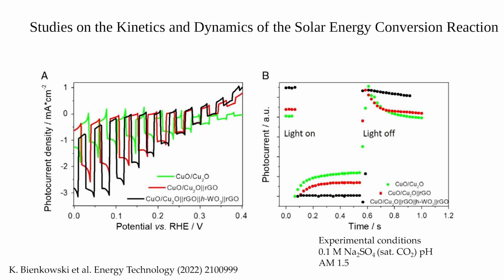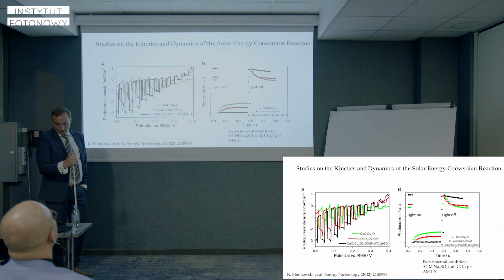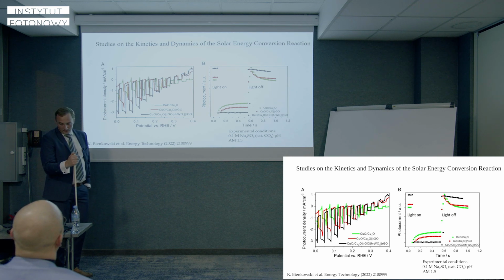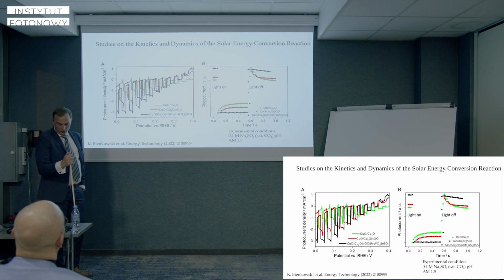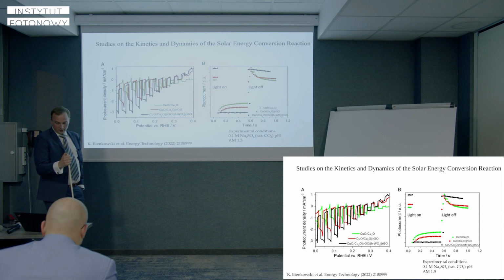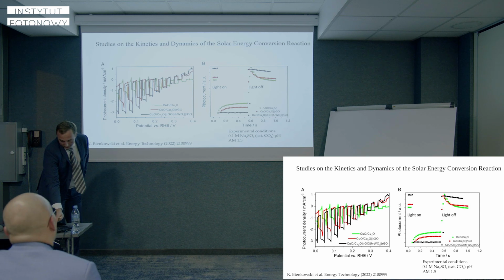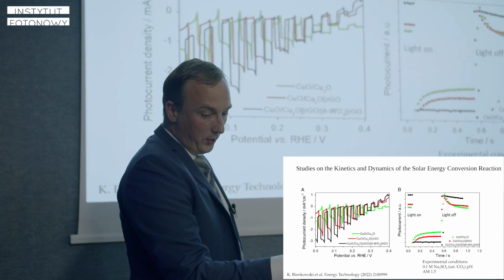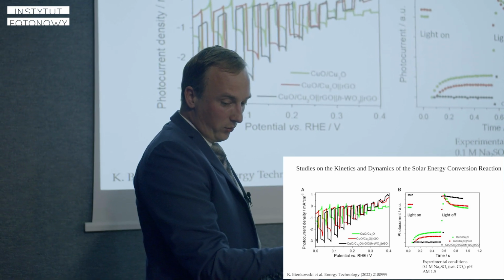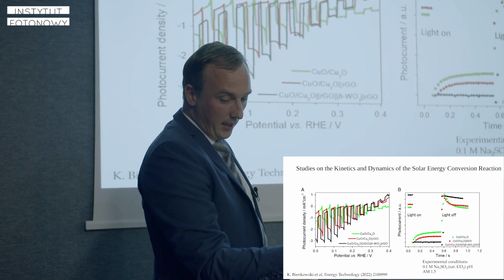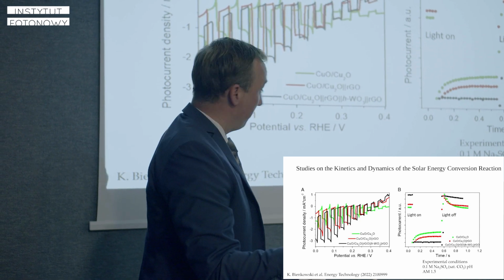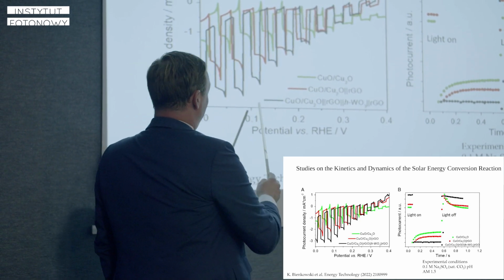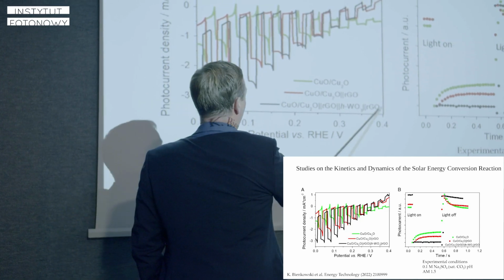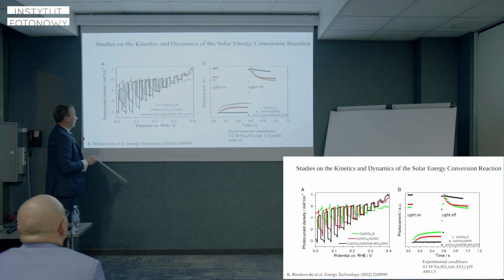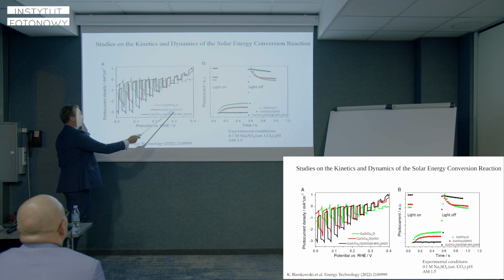some photoelectrochemical results. The advantages of RGO were observed in the hybrid photocathode for CO2 reduction. We selected a sandwich architecture for this application. By optimizing the RGO thickness and combining the nanostructure properties of materials with the unique matching between copper-1, copper-2 oxide and hexagonal tungsten trioxide, we eliminated the surface recombination currents.